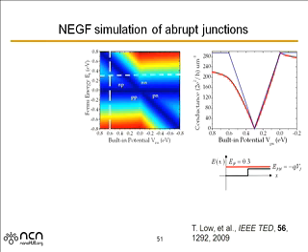And when Tony does these NEGF calculations, this is the plot that came out of the NEGF simulation. It looks very much like that MATLAB plot where we just asked, what is the minimum number of modes? It has the same structure and everything, but the numbers are smoothed and rounded out a little bit differently. And what you see here is that over on the P side, when the built-in potential is big, say 0.8, the Dirac point is way above the Fermi level, so this side is p-type. You can see a conductance. The NEGF treatment gives us a conductance that is significantly smaller than that simple minimum modes argument.